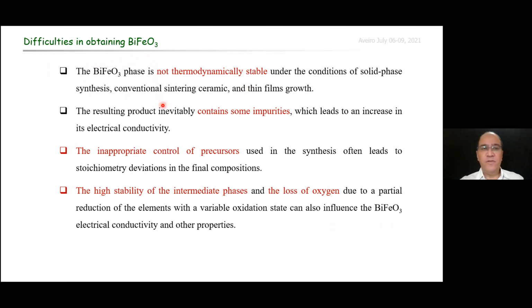As a consequence, different defects can be introduced in the BFO system during the synthesis of ceramics and thin films. Due to this instability, the final product often contains some impurities, which leads to an increase in its electrical conductivity. Other difficulties, such as the inappropriate control of precursors, the high stability of the intermediate phases, and the loss of oxygen can also influence the BFO electrical conductivity and other physical properties.